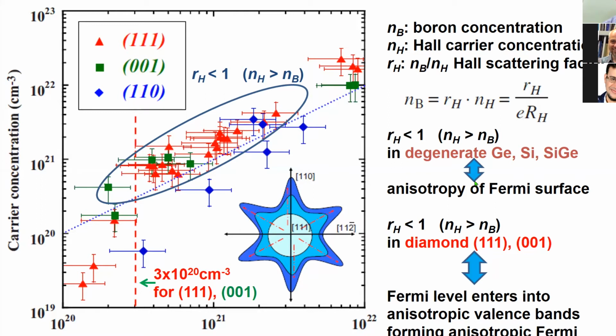The Fermi surface - we showed with ARPES spectroscopy that the valence band, the Fermi level, enters into the valence band and then we get this Fermi surface. But this is also very anisotropic.